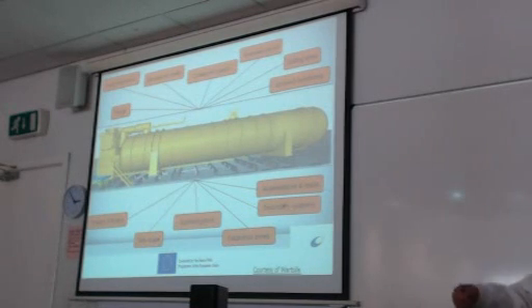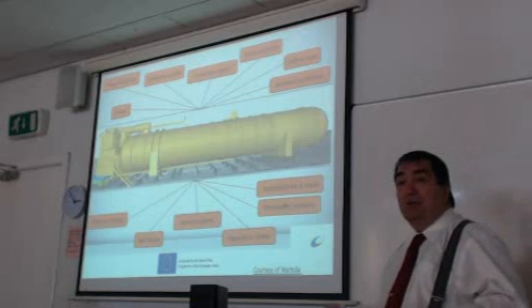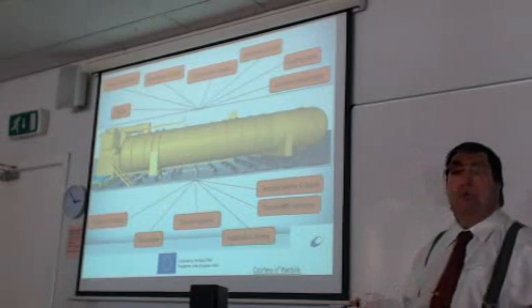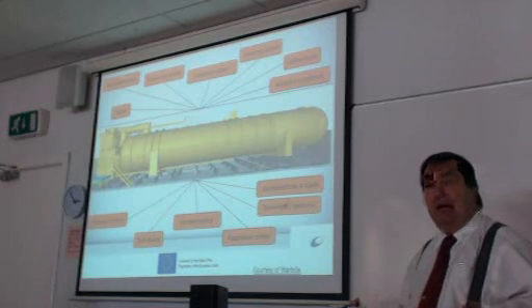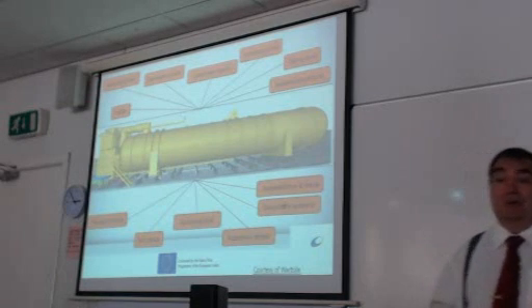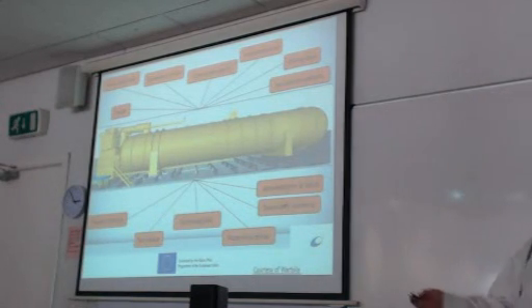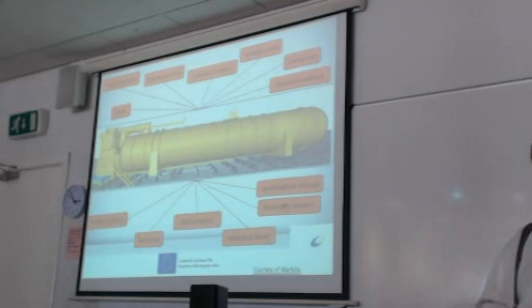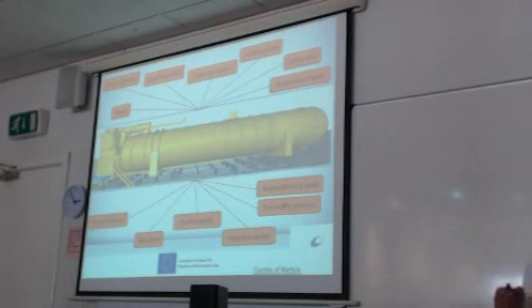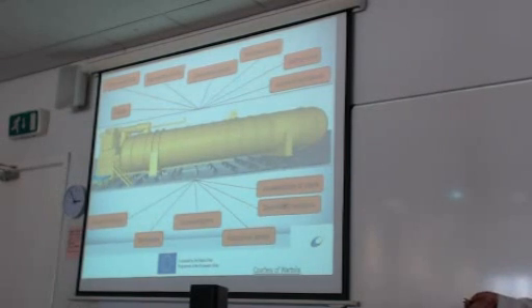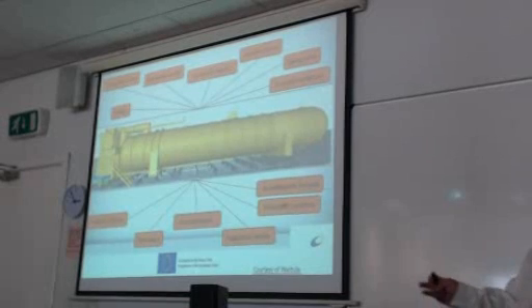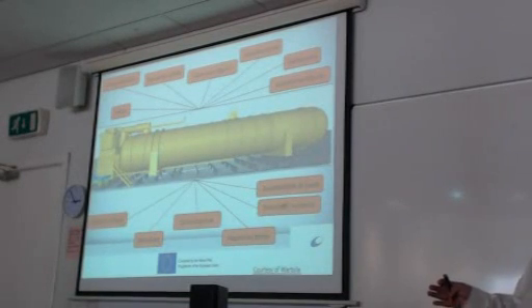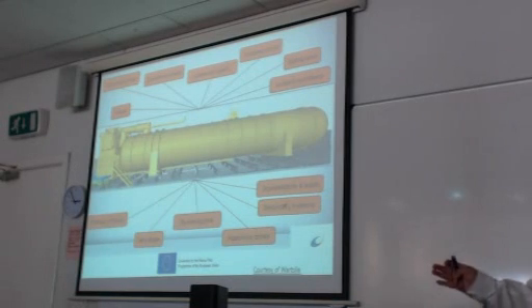Why do we do that? Because if this is connected with the hull rigidly, then the tank will follow the deflection of the hull. And we need to put additional loads on the tank. And I'm sure that the tank designer will not account for this type of loads. But we need to account for those. So we need to leave one support fixed in the longitudinal direction and the other free to move. How do we do that? Well, you can have elongated bolt holes, which of course you need in case you put a cold liquid, when we put the cold LNG in the tank.